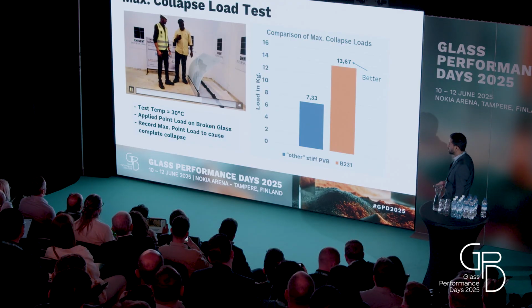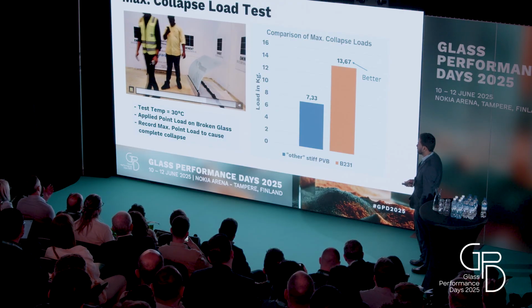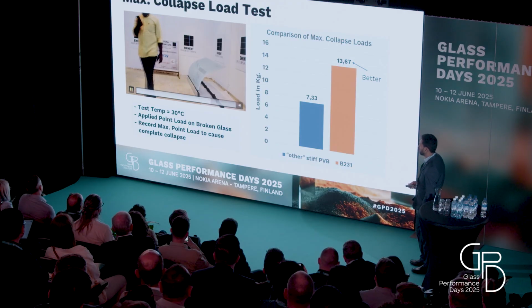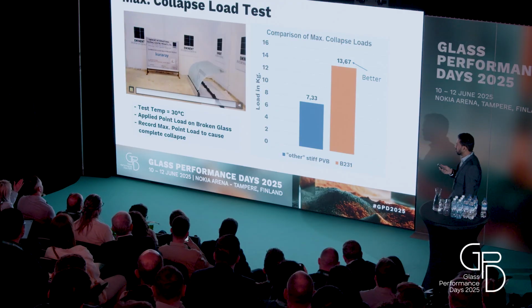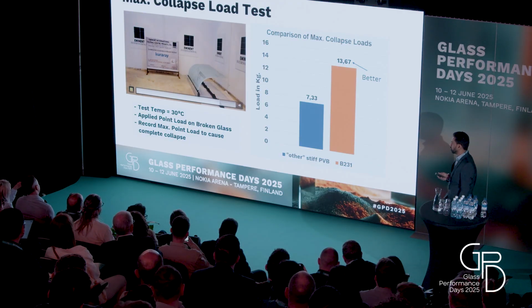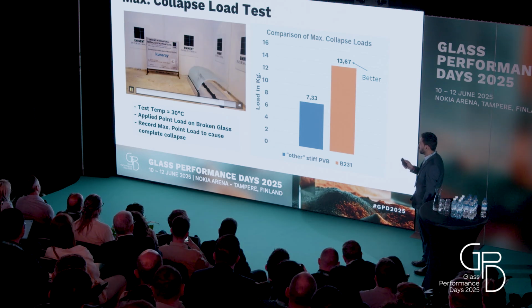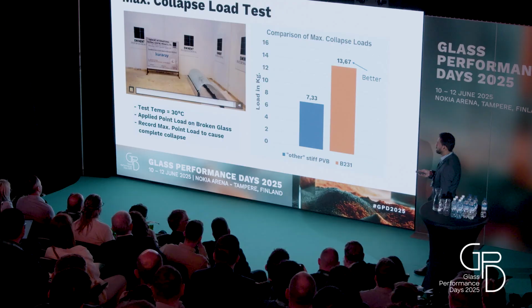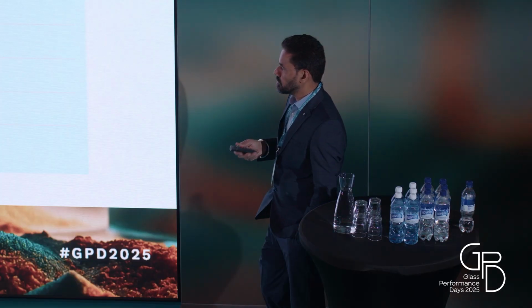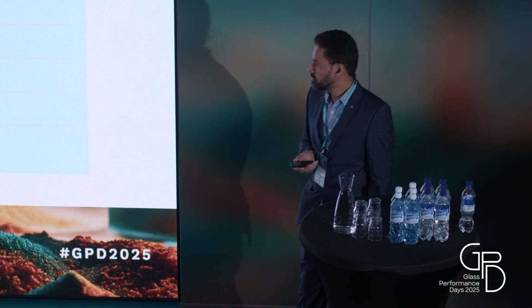This test was done at one of the test labs in Hyderabad, in India. It was hard to find a lab with a temperature-controlled environment. So the lab had to create a special setup for us so that there is no variation of the temperatures, because even a little variation of temperatures can actually cause a lot of difference in the structural performance.